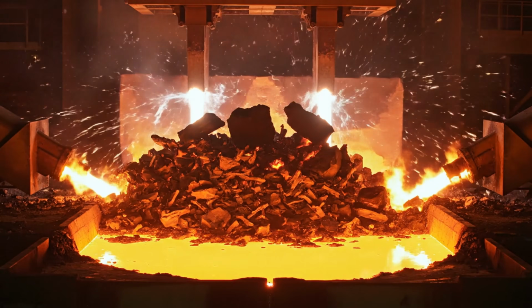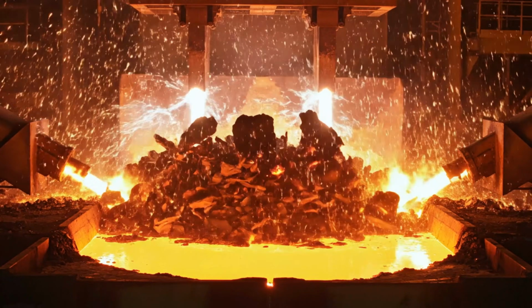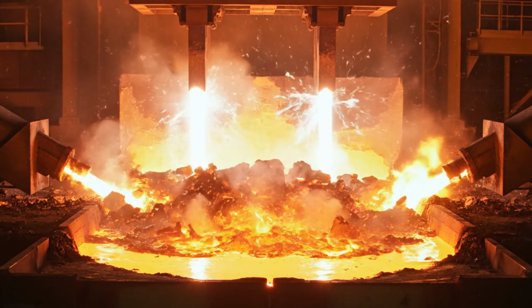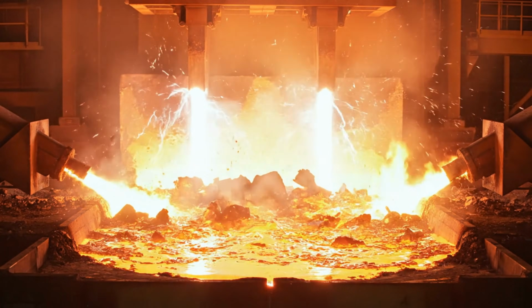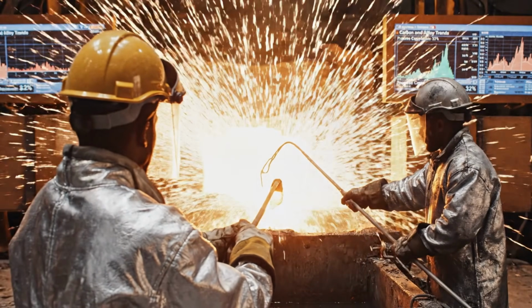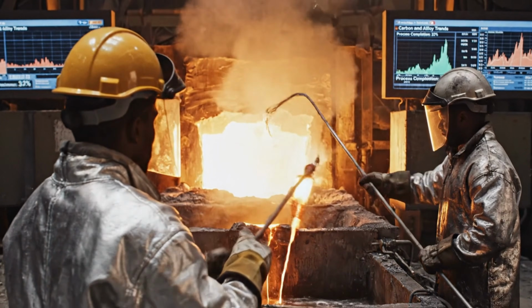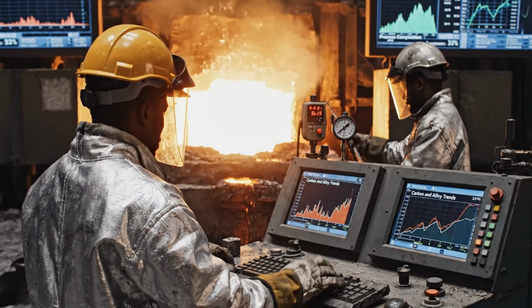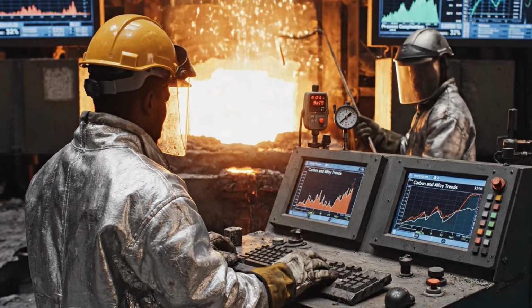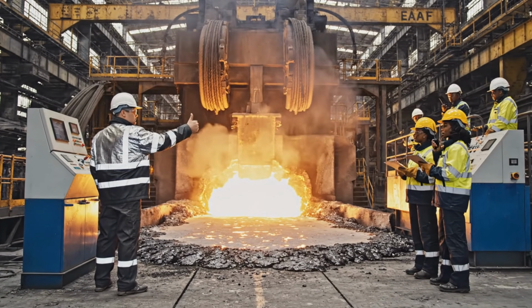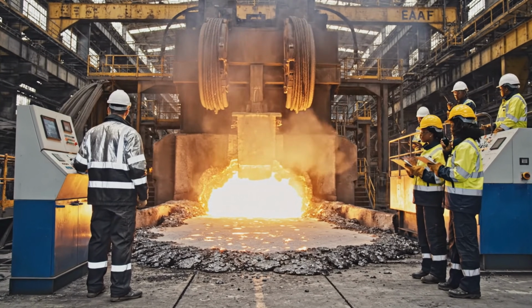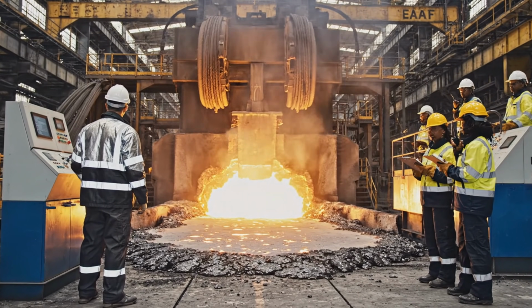The furnace continues melting until the entire charge becomes one liquid mass. At this stage, operators check chemistry and temperature to steer the melt toward the target grade. Once chemistry and temperature align, the heat is ready to leave the furnace.